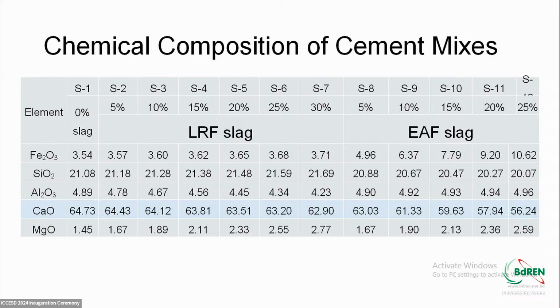After replacement, the chemical composition became like this. In LRF, the ferrite percentage was comparatively less, while when EAF slag was used, ferrite percentages increased with a higher portion of EAF slag. Lime percentage remained relatively similar to clinker in the case of LRF slag, but lime percentage was reduced in the case of EAF slag.